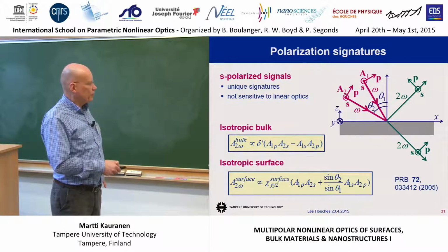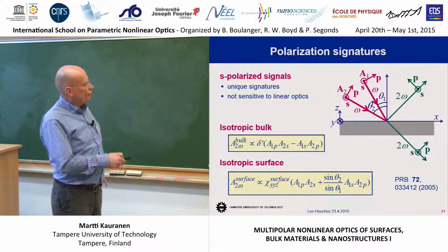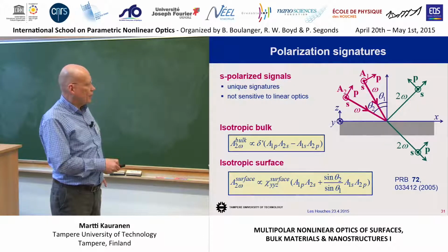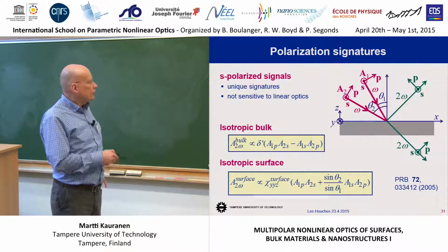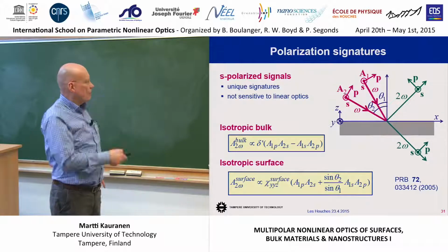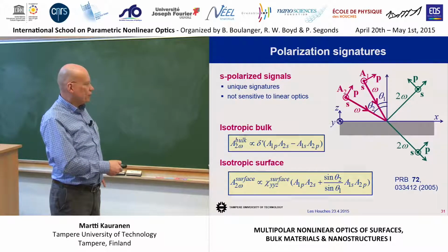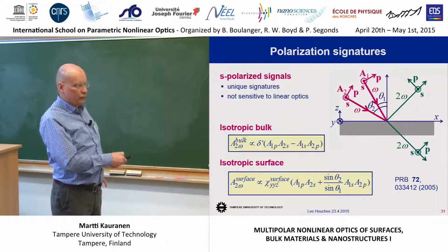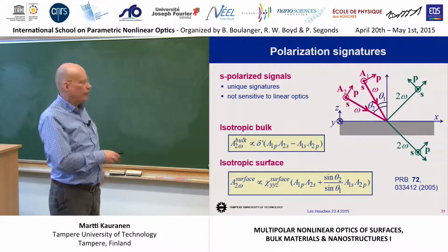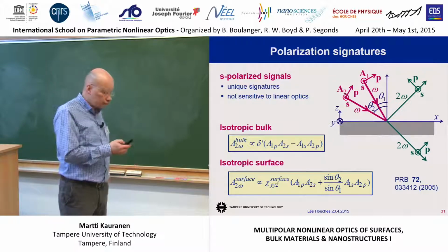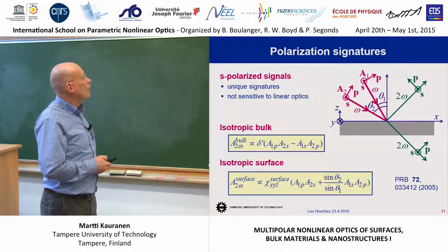Here it depends on the angles of incidence. And now if the two beams come from the same side, we get a plus sign here. So in some sense, when we do this polarization scan, we have an in-phase contribution between the two terms from here, and an out-of-phase contribution from here. So we can expect very clear signatures. Okay.